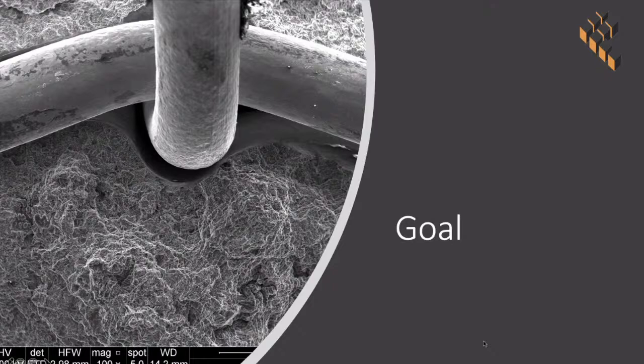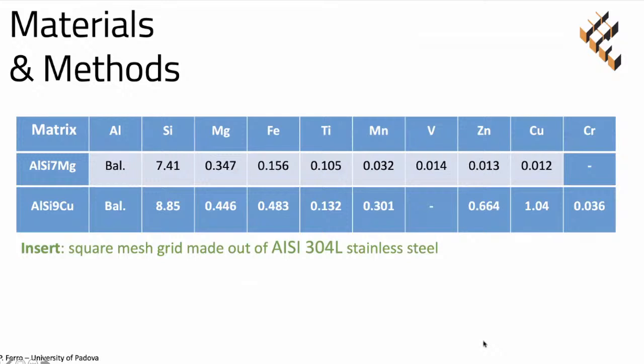In particular, we tried to investigate the effect of two different aluminum alloy compositions, in order to investigate the influence, of course, of the alloy elements on the interface between the matrix and the insert. We use these two aluminum alloys as matrix. The first is aluminum silicon 7 magnesium, and the second is aluminum silicon 9 copper. The main difference consists in the amount of silicon and of course also in the amount of copper.